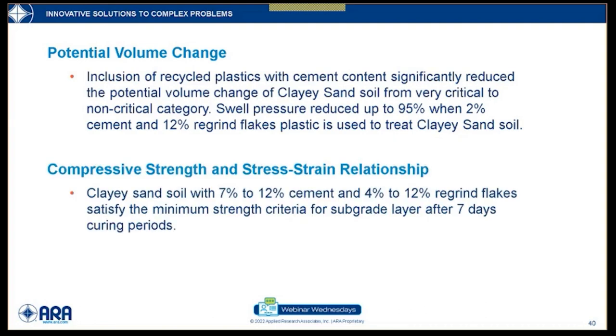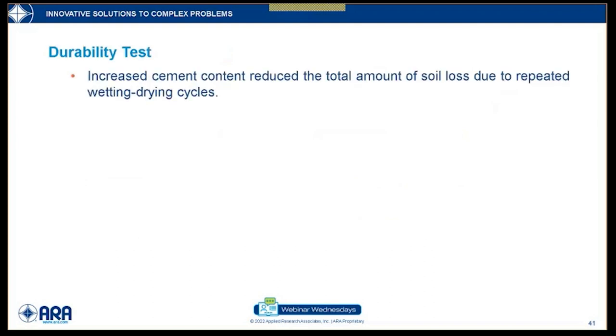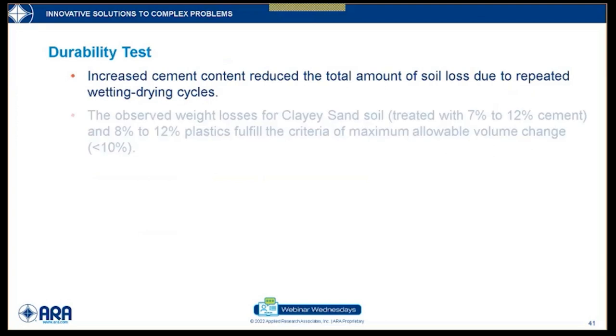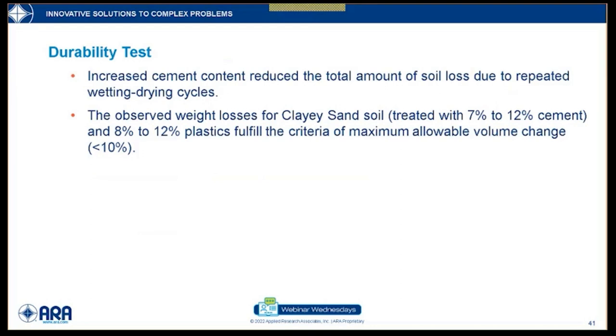And the compressive strength shows that when the recycled plastics are mixed in with the cement, with desired cement dosages and desired waste plastic contents, some of the mix designs can satisfy the minimum strength criteria of the soil pavement layer. And the durability test shows that increased cement content can reduce the total soil loss amount. The soil cement mixed with certain dosages of cement and plastics can also satisfy the maximum allowable volume change criteria, that is less than 10%.